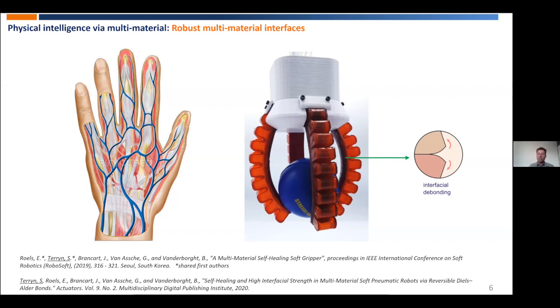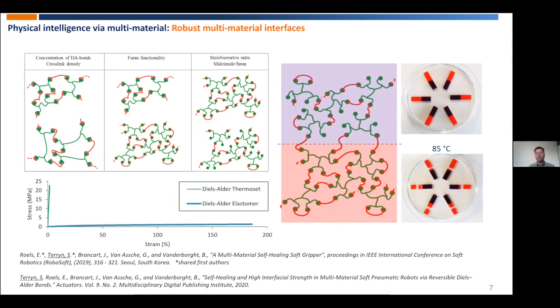And one main challenge is that the interface of these different materials causes usually some problems because of this interfacial debonding. And this leads again to systems which are not robust and which have a limited lifetime. Now, the materials that we make, they can also provide a solution for this.